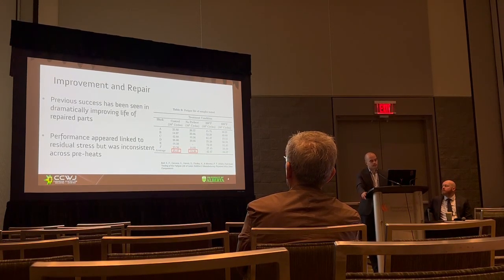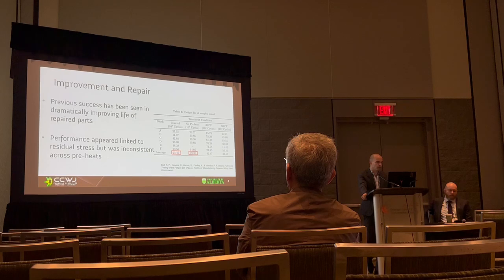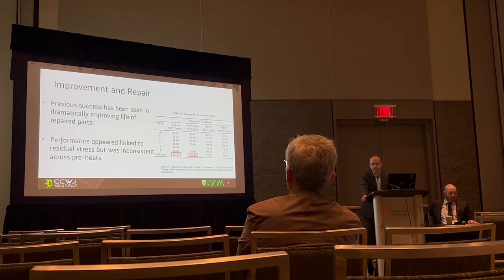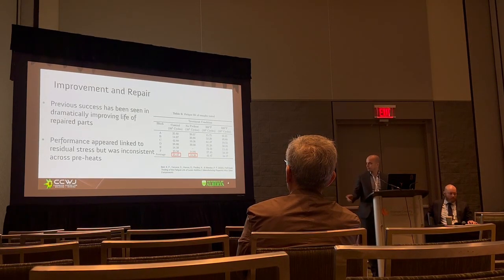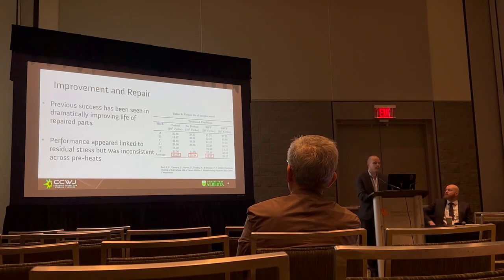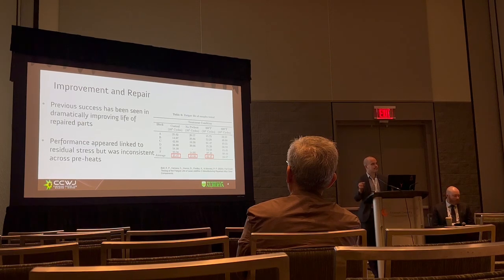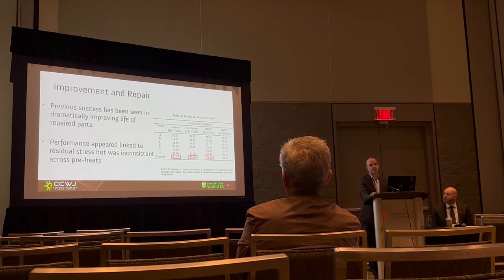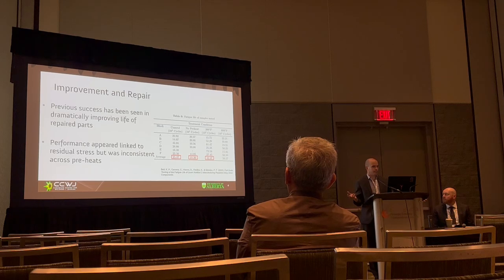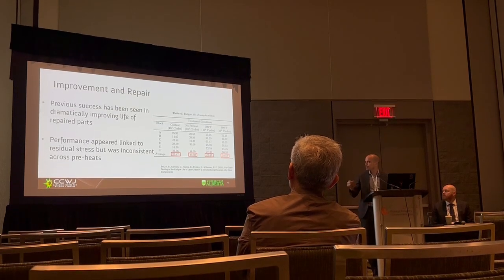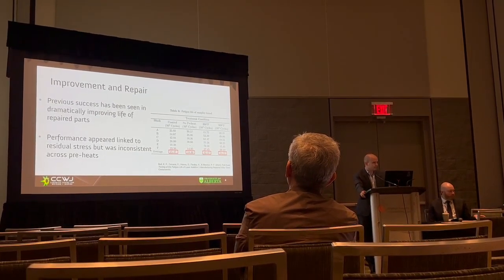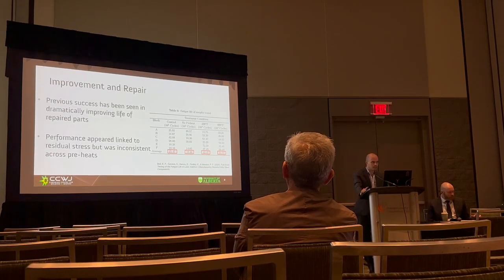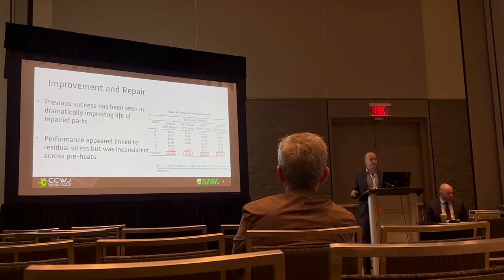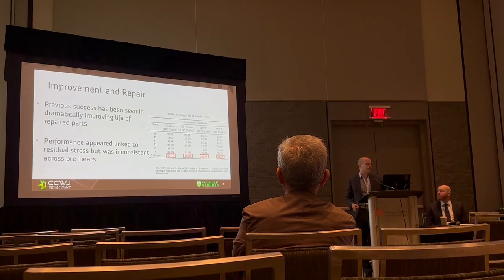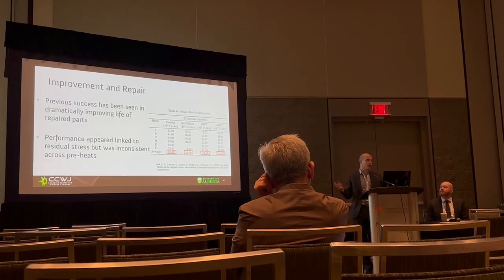Then they tried welding it. And they were putting on like a 13 chrome alloy steel, and when they welded it, it didn't work very well. Yet, you know, a little bit more than half the lifespan. It's okay for repair, we can live with that, whatever. Then they preheated it to 300 degrees, and it outlasted the part as manufactured by almost double the lifespan. So that was weird. Okay, preheat helps. Maybe we keep going, we'll preheat to 600 degrees Fahrenheit. It got worse. So preheat helped, then it made it worse. What's going on? They published this data. They basically told the guys, yeah, we can repair it, preheat to 300 degrees, you're gonna get a great lifespan, and they kind of moved on.